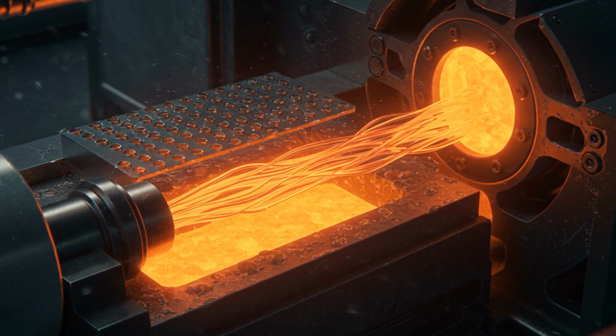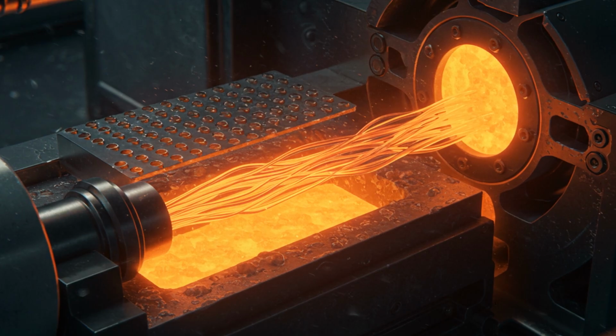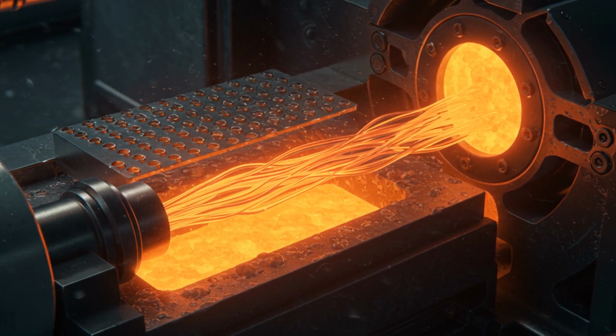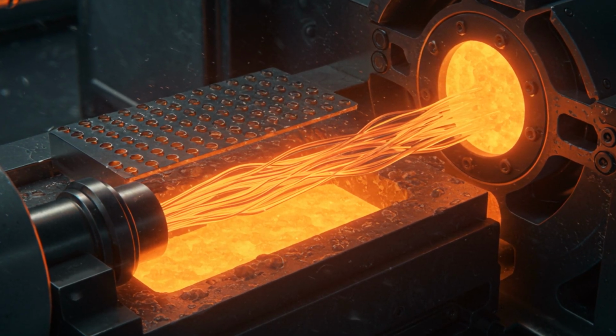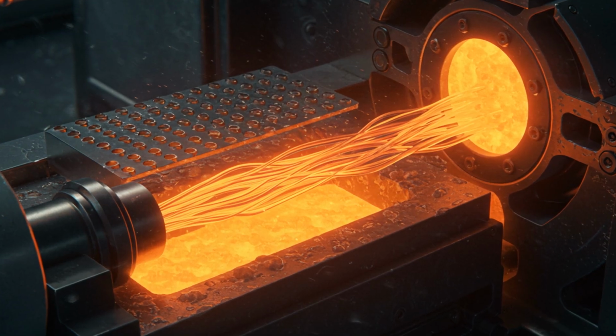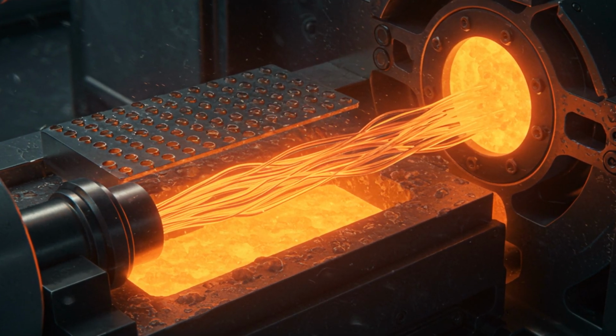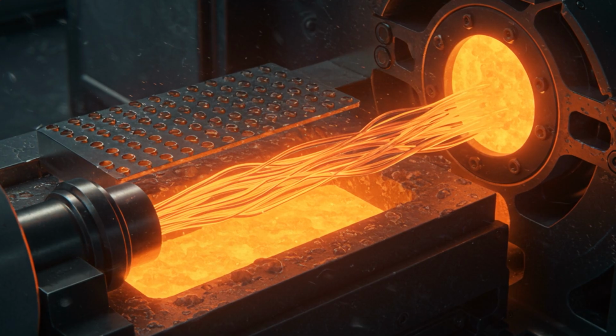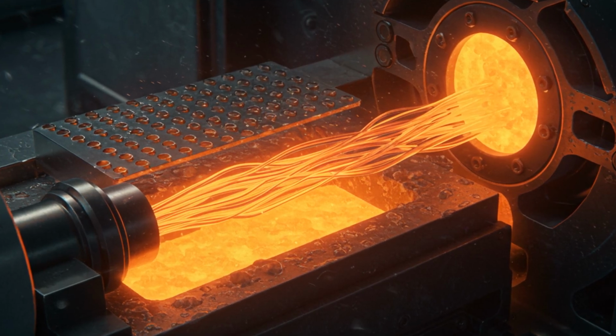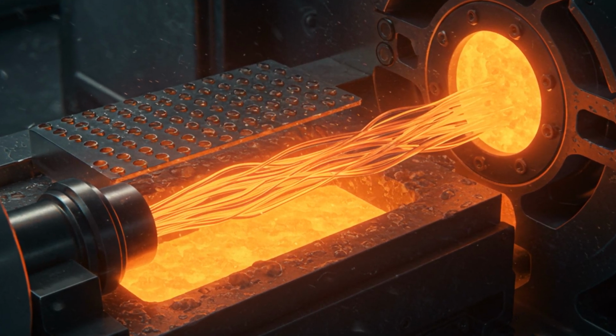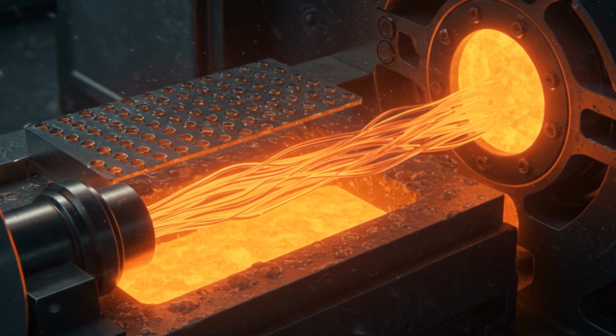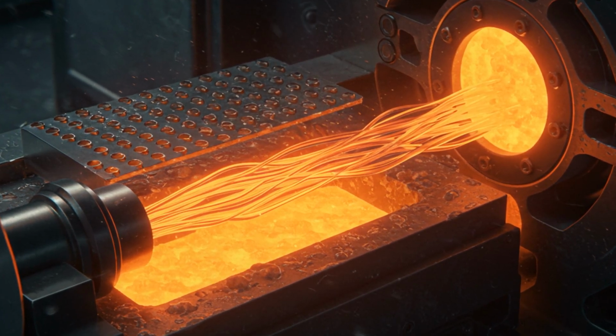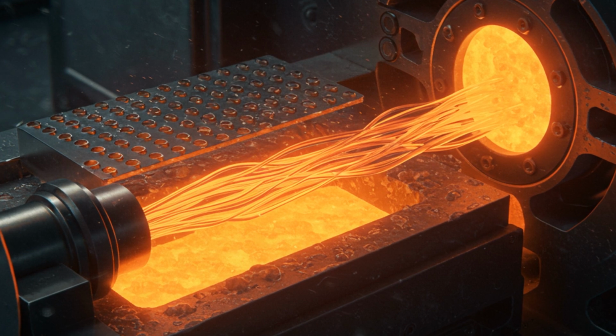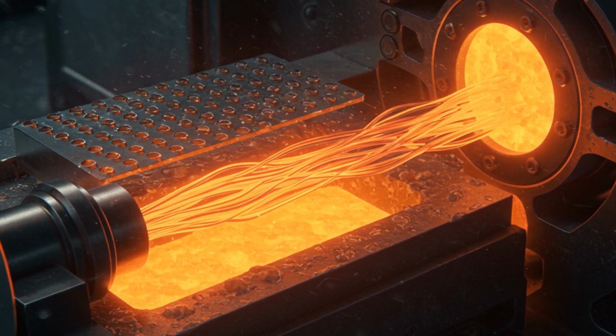Immediately below the spinneret, a quench chamber with controlled cooling air solidifies the filaments into fibers. Control lines adjust air velocity, humidity, and temperature. Too rapid cooling locks in amorphous structure. Too slow allows sagging and breaks. Take-up wheels pull fiber at speeds of up to 2,000 to 3,000 meters per minute, stretching them gently as the extruder maintains constant pressure. Spinnerets are precision ground because a microscopic imperfection creates a weak point.